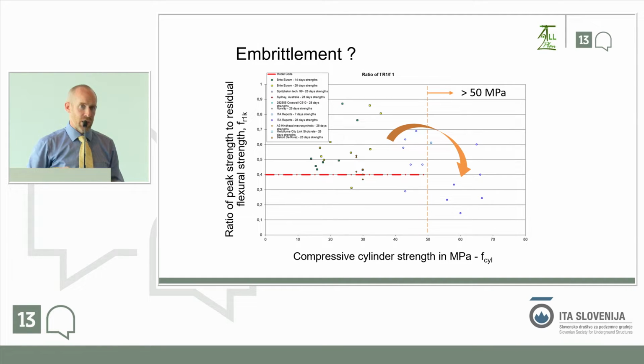And this is where you then look at the values of different strengths. A point that was mentioned, I think, earlier on is the effect of strength, that we're making some very high quality concrete. Some examples from yesterday were strengths at 7 days, I think, of 37 MPa. This is for a 25 MPa mix. At 28 days, I think it was about 48. And Wolfgang was commenting about how you test at a year and you might find it's at 60.